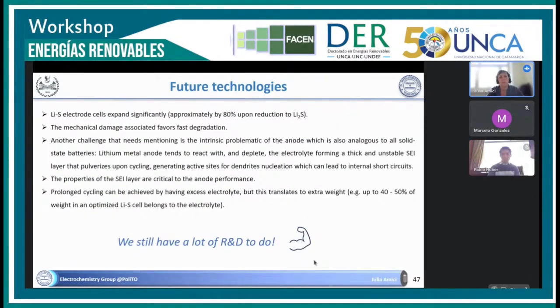Another problem is that both sulfur and the lithium polysulfide are electronically insulating, meaning that if they deposit too much on the anode or the cathode, they block the transfer of electrons, and so they block the electrochemical reaction. Also, the lithium sulfur cathode expands a lot during charge and discharge, so they tend to suffer delamination or cracking of the electrode. So there is still a lot of research to be done.